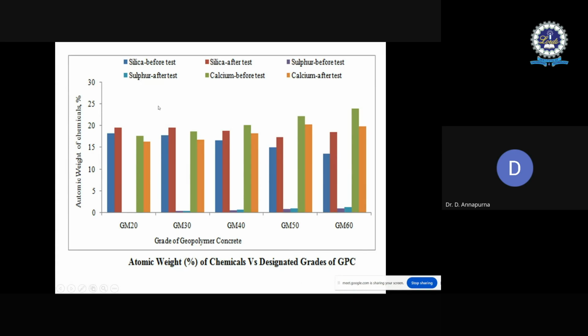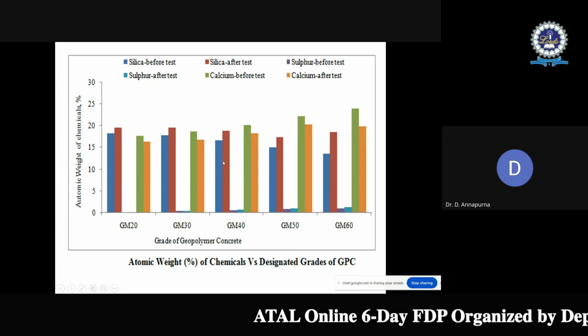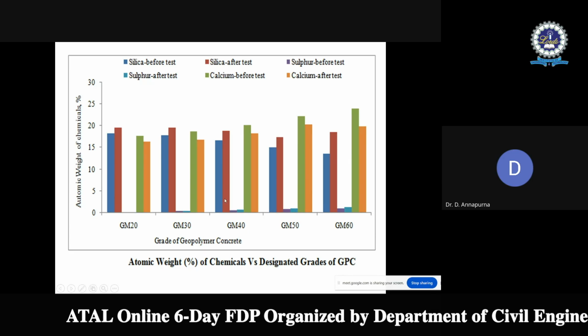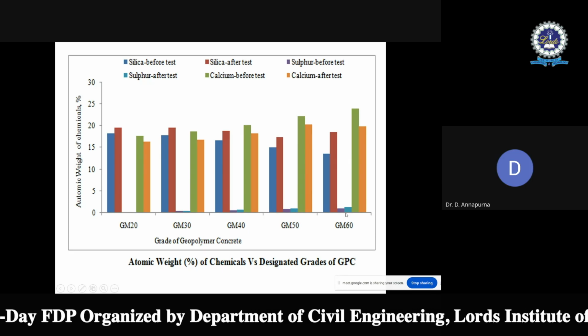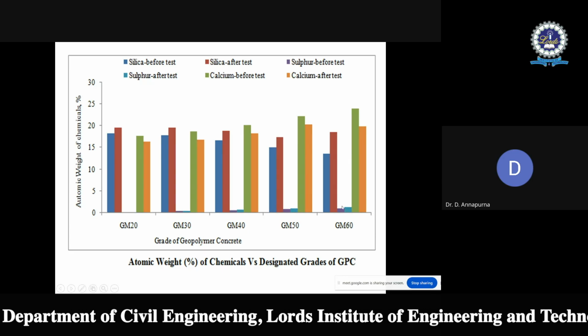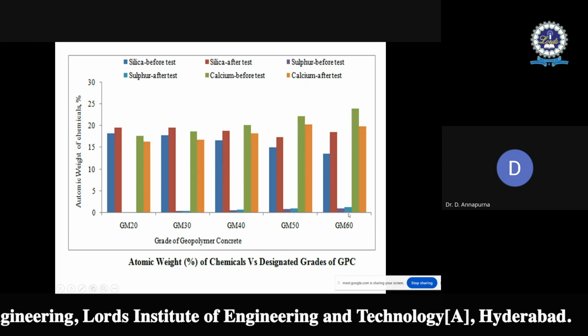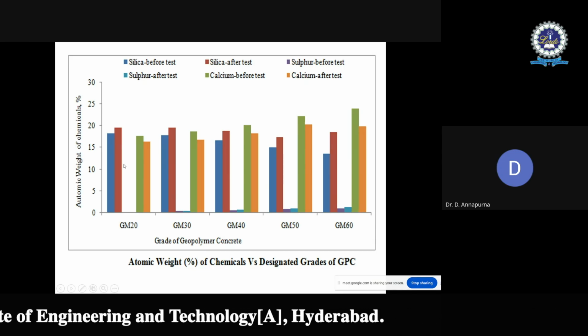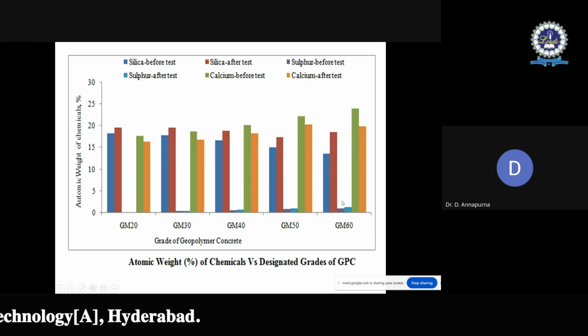concentrations. The same is depicted again through the atomic percentage weight of the samples. As the grade of geopolymer concrete increases, sulfur content also increases. That means the effect of sulfuric acid is more on the GM60 samples than on the GM20 samples. So this is about acid exposure.